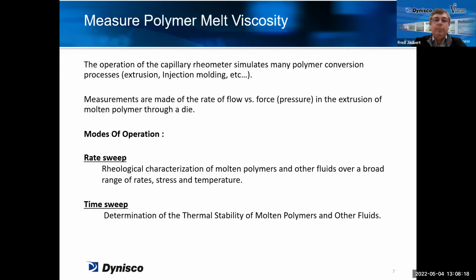So again, what are we doing with a capillary rheometer? We are measuring the melt viscosity of a polymer. So basically, as I was showing earlier, we are simulating exactly the same process conversion, especially as injection molding. Injection molding, first, you have a screw, of course, which is there to mix the polymer, but then the second step is really to push the polymer through a nozzle and through channels into the mold, which is pretty similar to what you do when you are pushing the material through the capillary die of a capillary rheometer. So the principle of the measurements are made of the rate of flow, so versus the force. So the rate of flow is the shear rate, and the force will be converted to the viscosity of the product.